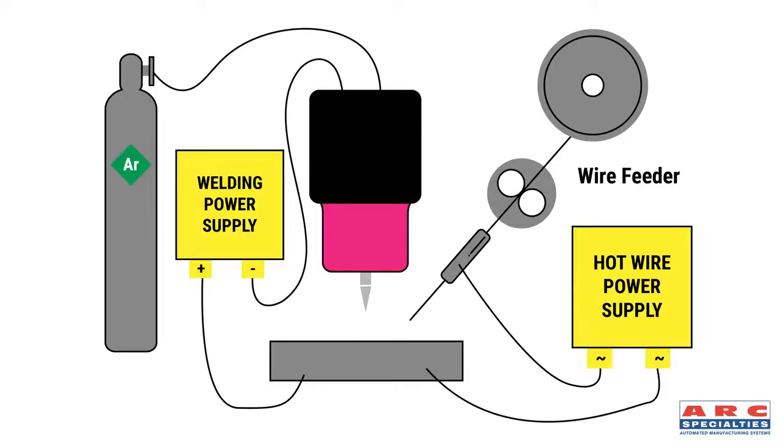We connect one of the electrodes to the workpiece and the other to a contact tip, much like in a MIG torch. This contact tip conducts between 1 and 5 volts and between 10 and 150 amps into the wire. This preheats the wire as it goes into the weld puddle and allows you to reduce the current necessary on the gas tungsten arc torch itself.